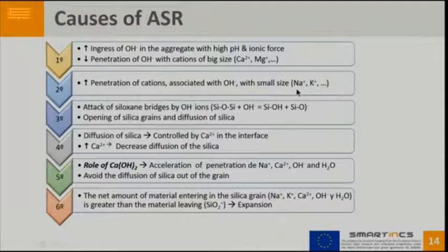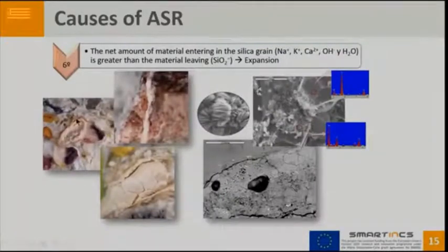Well, we can see a stereomicroscopy image here. There are some aggregates completely attacked by alkalis. Here also, this is an opal, and the damage or the reaction goes from the surface to the interior.